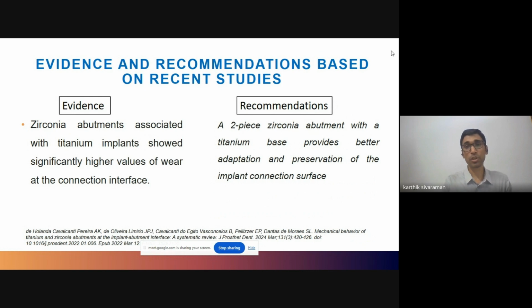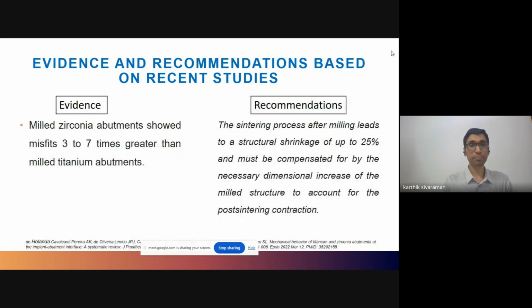So the recommendations of the authors are that in case you plan to use an internal connection treatment, and you're providing a two-piece zirconia abutment with a titanium abutment or tie base, will be better. It will ensure a better adaptation and preservation at the implant connection surface. So go ahead with a zirconia abutment with a tie base to ensure the less wear of the interface.